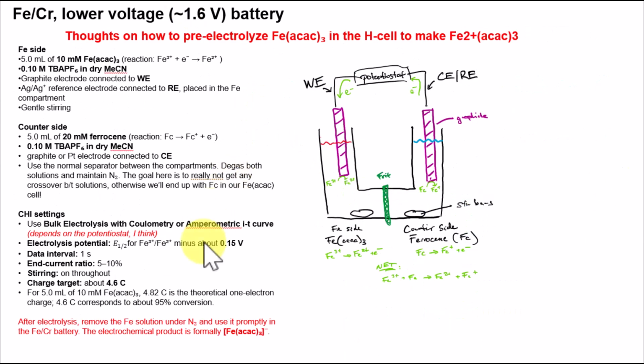And this slide captures some general notes on how you might pre-electrolyze the original iron 3 ACAC into an iron 2 state using the same H cell. So we did this with essentially a 3-electrode cell. There's a more updated version of this, but we effectively took the iron compound, the iron 3 ACAC, in the left side of the cell with the working electrode. We used carbon rod here, and we actually put the non-aqueous reference electrode also in this same side.